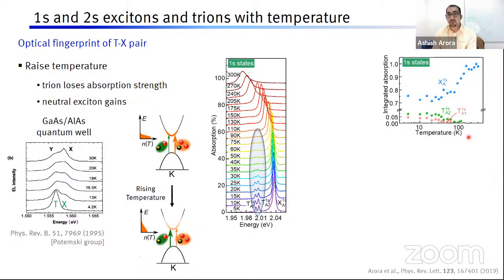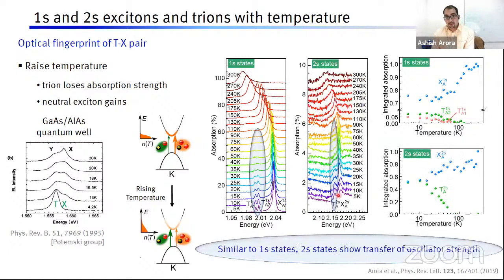Now let's see if this transfer of oscillator strength also fits for the case of 2s states. So we have this 2s trion and 2s exciton, and what we notice is the same, that when we raise temperature, 2s trion loses strength, whereas 2s exciton gains. So similar to 1s states, 2s states also show transfer of oscillator strength, which is another piece of evidence that what we are seeing here is a connected set of excited states of trion and exciton.